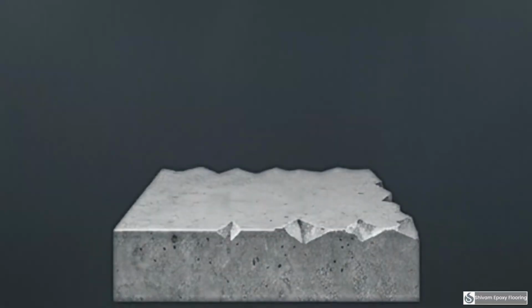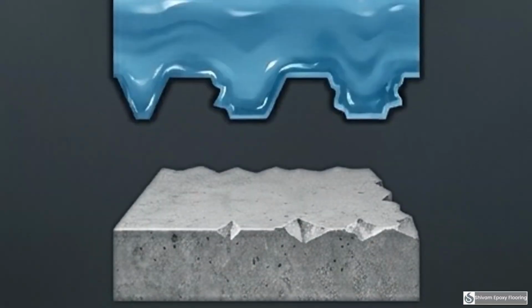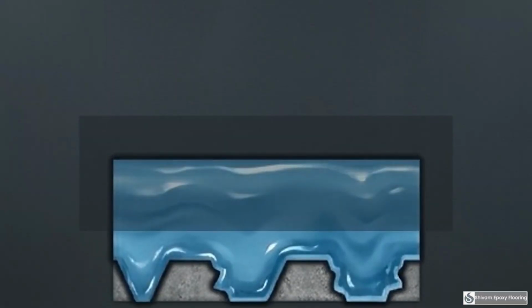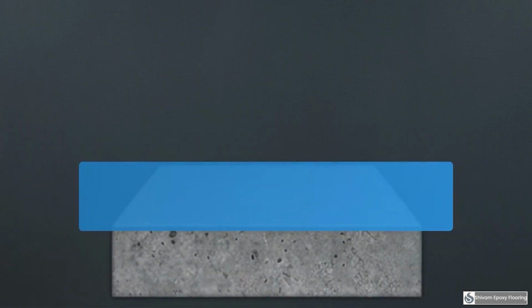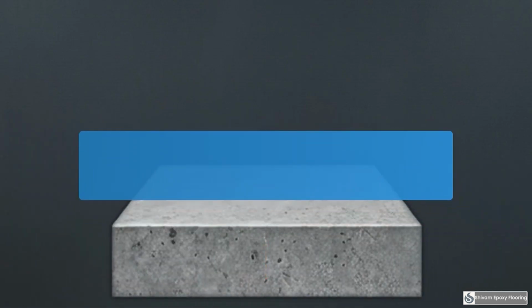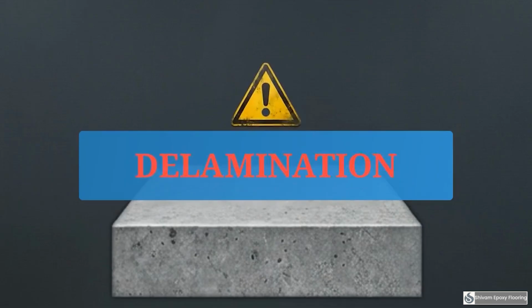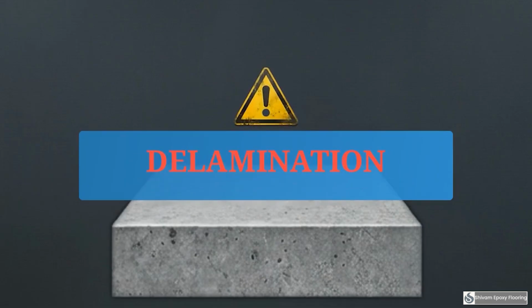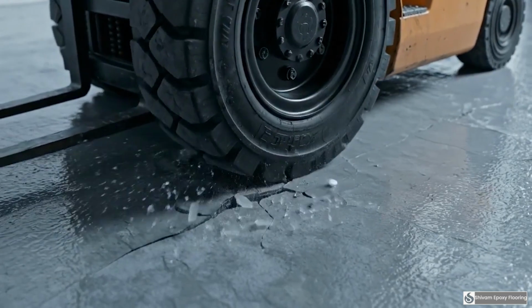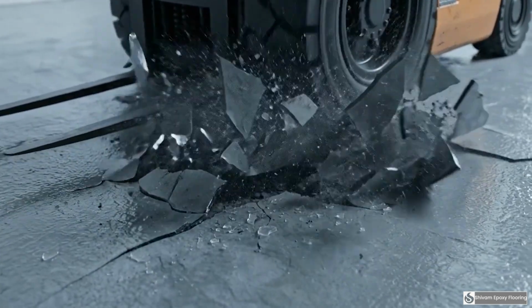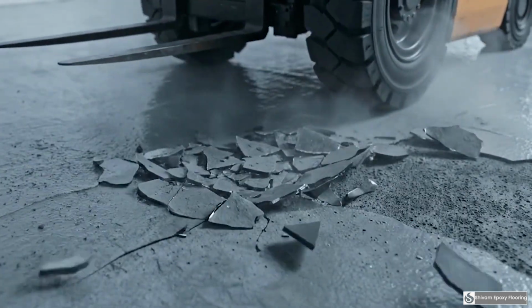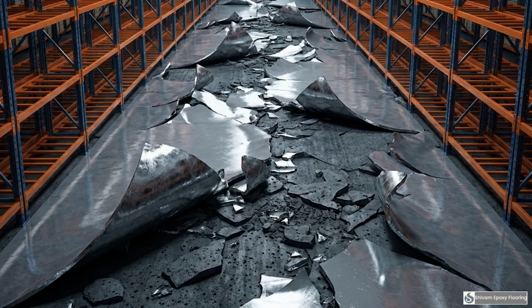This diagram illustrates why grinding is necessary. Liquid epoxy flows into jagged peaks, locking into the concrete. An acid wash leaves the surface too smooth. Under stress, the hardened epoxy separates from the concrete, a failure known as delamination. The heat and friction from turning forklift tires can then easily peel that weakly bonded epoxy right off the floor. Bypassing proper diamond grinding guarantees catastrophic peeling, which makes any initial savings worthless within a few months.